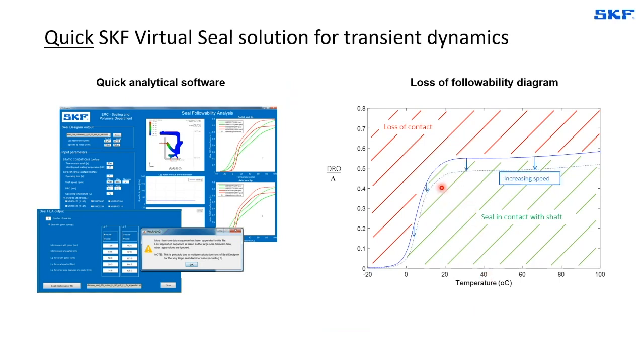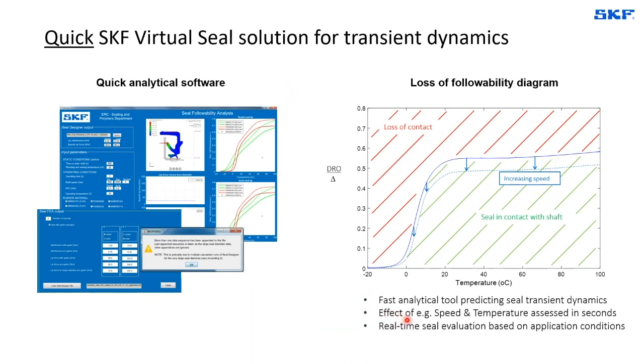Then what happens here is that as we increase the speed, remember again the ball experiment, the area that is effective for the seal, where the seal remains in contact, starts to reduce. And this ultimately will lead to failure. And we are able to predict this analytically. So having a fast response, allowing us to capture the transient dynamics of the seal with the effect of speed and temperature assessed in seconds, really, because there is absolutely no computational time except entering your parameters here, allows us, like I was saying, to evaluate the seal in real time and to respond to application changes if need be.